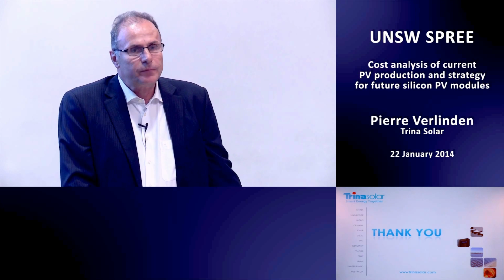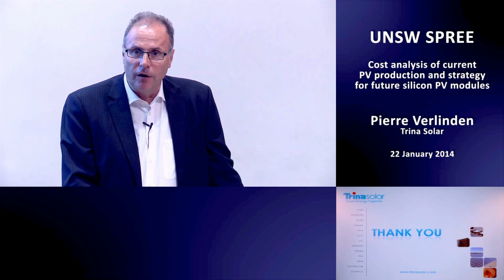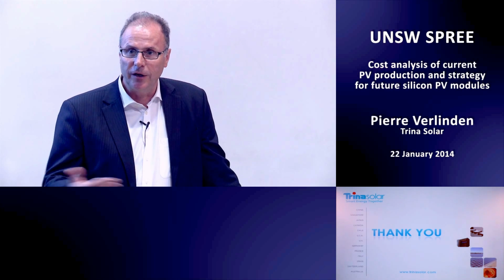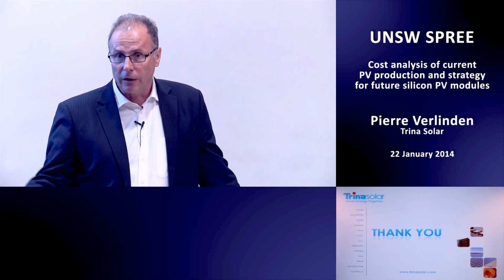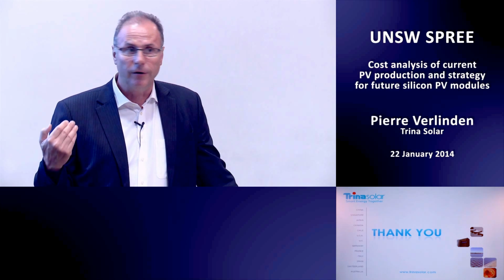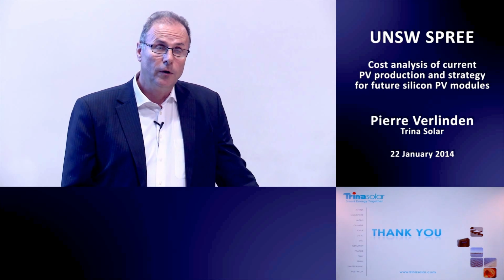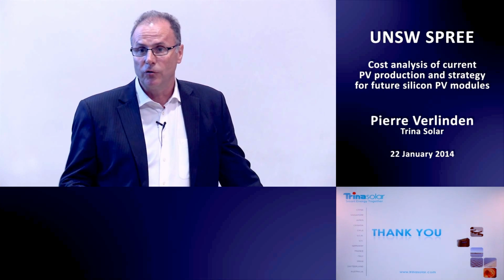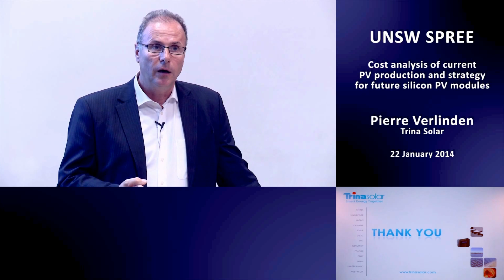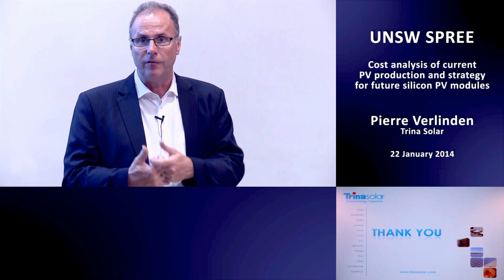Okay. It's very difficult to have real data. Of course, we have testing, we have thermal cycling, humidity, freeze, damp heat, etc. How does that relate to the real degradation, the real world? Well, it depends very much on the climate. You're not going to have the same degradation in Alice Springs or in Shanghai. So there is not one answer for one module. There's a multiple answer depending on the climate. Even there, we don't know that relationship because we don't have enough time.